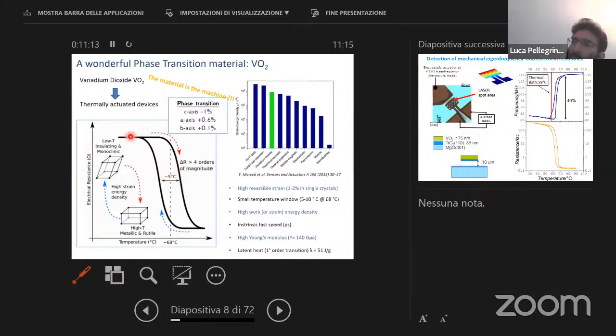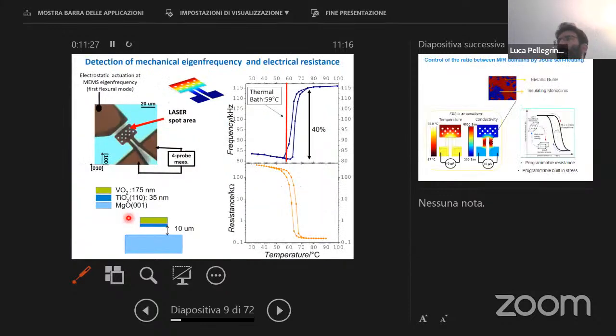but I would also like to focus on the fact that this transition from a low temperature insulating to a high temperature metallic state has a hysteresis, and in this temperature window you have a mixed state between these two phases. I will show you how we can detect this mixed state.